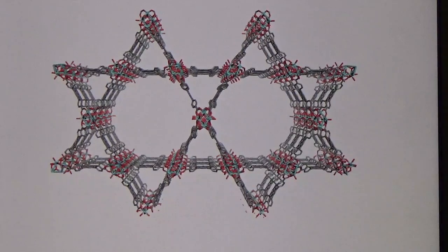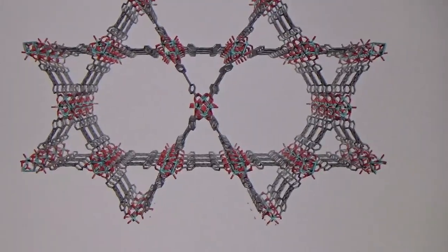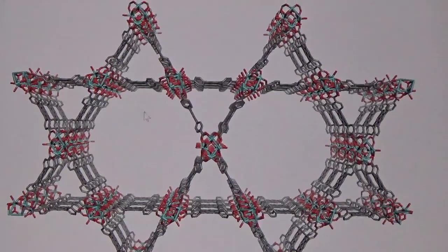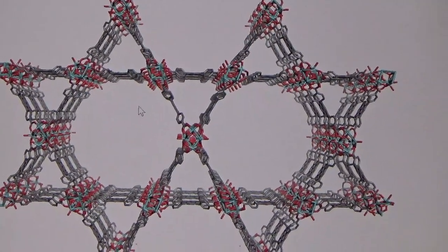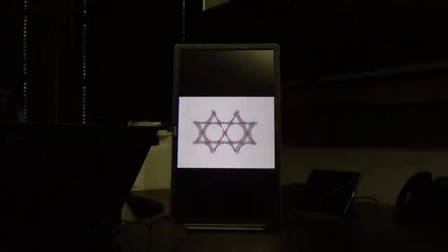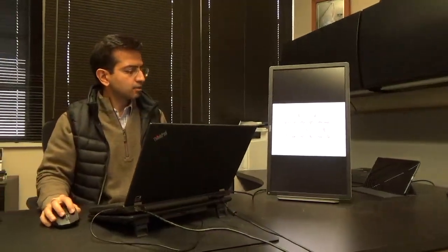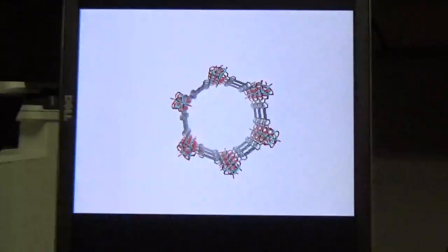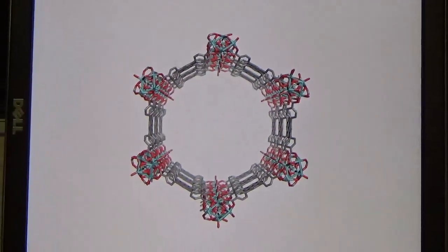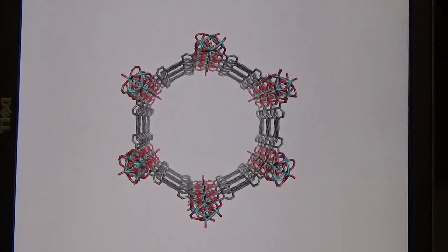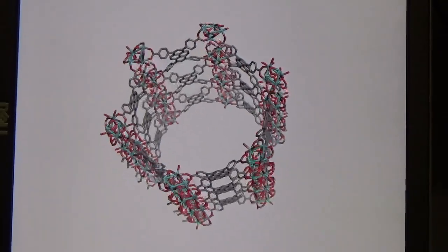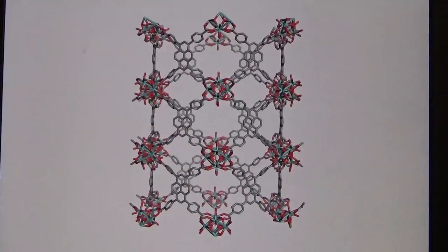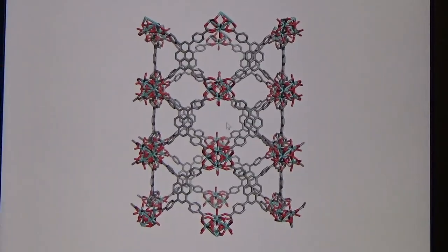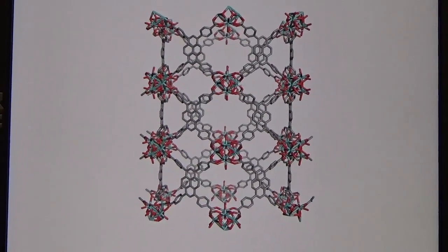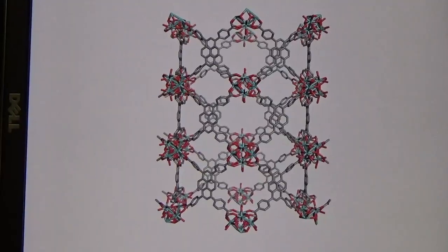So you can see that we have two types of channels. One channel is hexagonal and the other one is trigonal. Here we have a diameter of about 30 angstrom, or 3 nanometers, for this hexagon, and you can see that when we look at different angles, we have linkers and we have the metal cluster, which are stitched together. Here is another view; even from this angle, this material is porous, showing the linkers and the metals which are connected together.